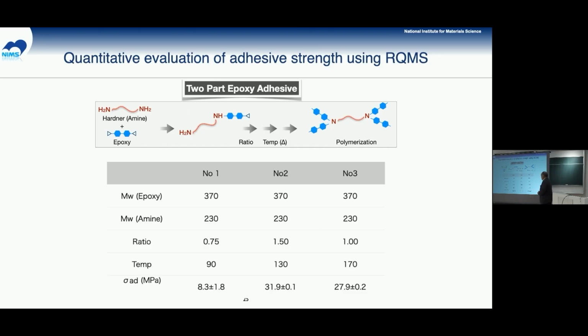Okay. So we use our method to analyze the performance of the adhesive after curing, in network polymers. As a demonstration, we use the very common two-part epoxy adhesives with diamine systems. By changing the composition ratios and the process conditions, we get several different types of adhesives with different adhesive strengths.